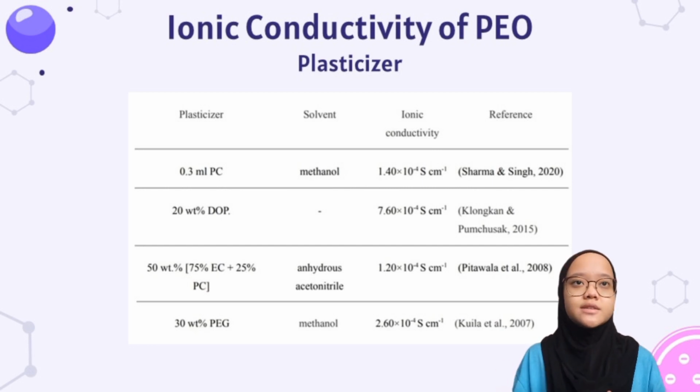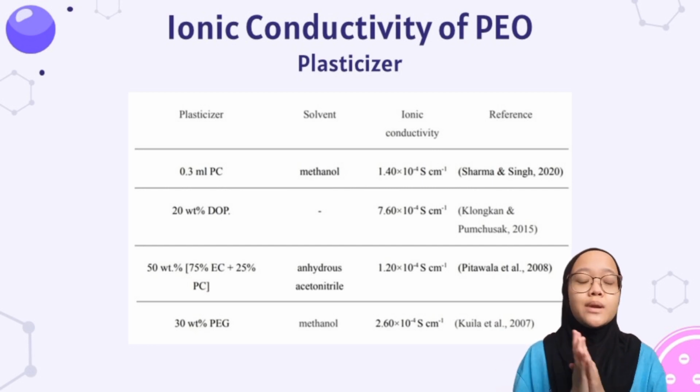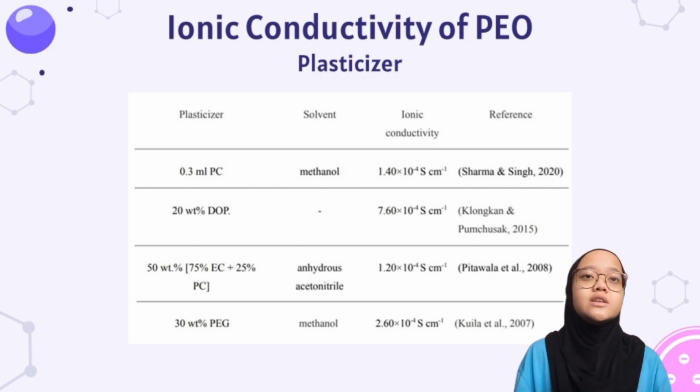Pitawala and others worked on an experiment to observe the effect of plasticizers, EC or PC, on the ionic conductivity and thermal properties of the PEO mixed with lithium triflate mixed with aluminium oxide nanocomposite polymer electrolyte system. In the experiment, PEO mixed with lithium triflate was dispersed with ceramic filler, which is aluminium oxide, and plasticized with propylene carbonate PC, ethylene carbonate EC, and a mixture of EC and PC. A mixture of plasticizer EC and PC further demonstrated the greatest conductivity improvement in the targeted temperature range, yielding a value of 1.2 times 10 to the power of negative 4 S cm-1.